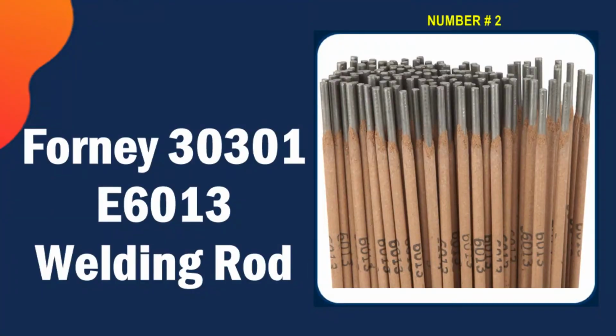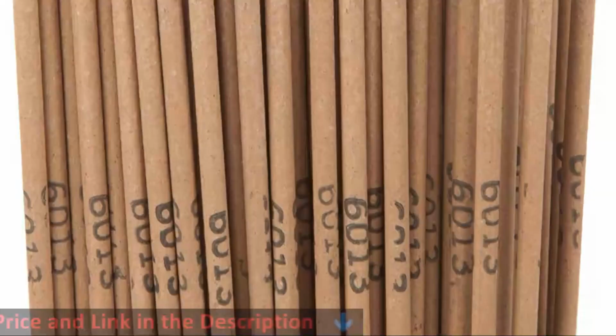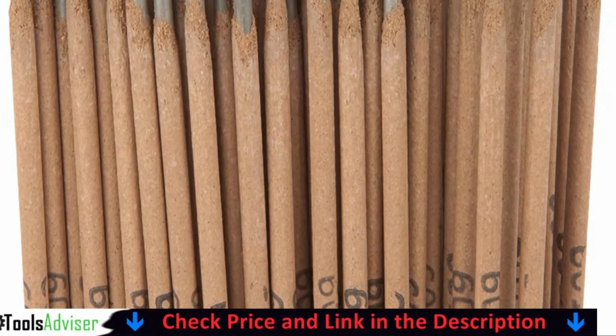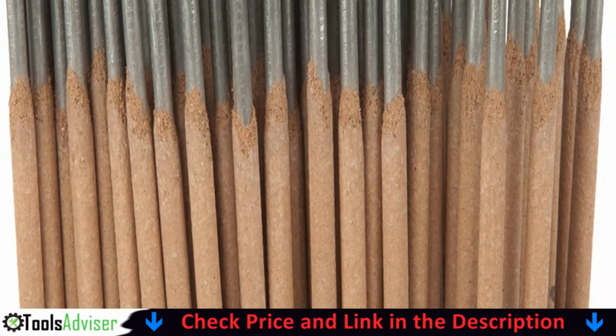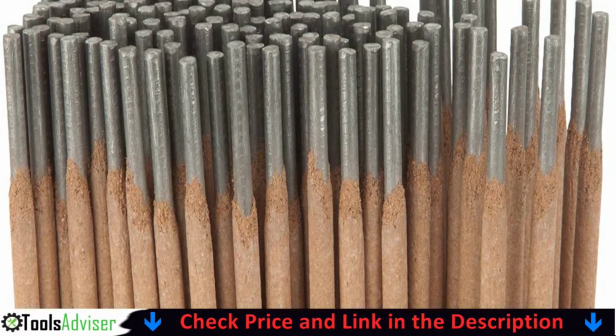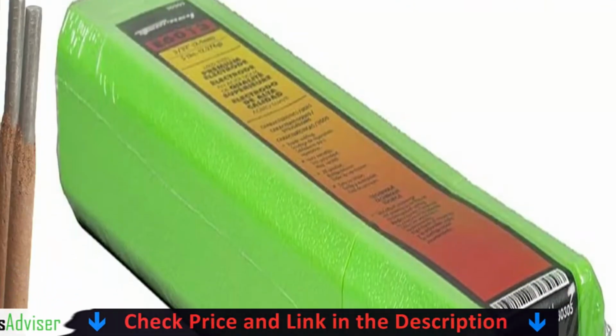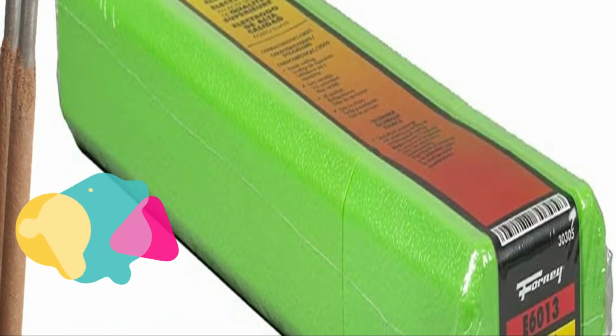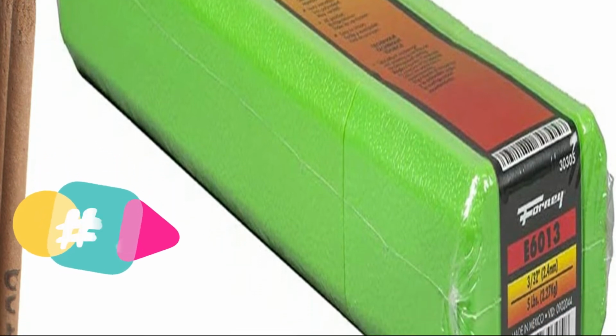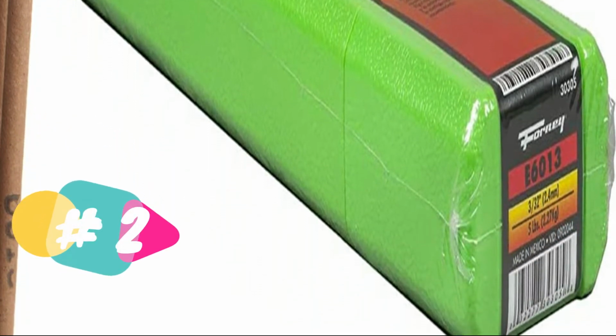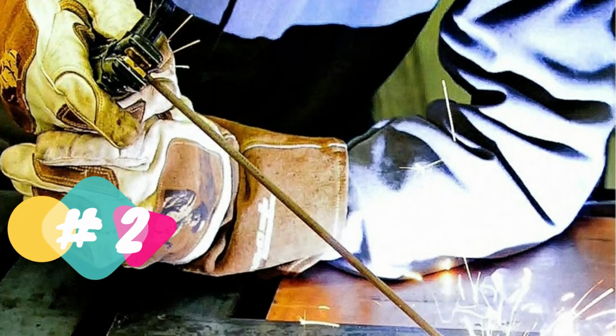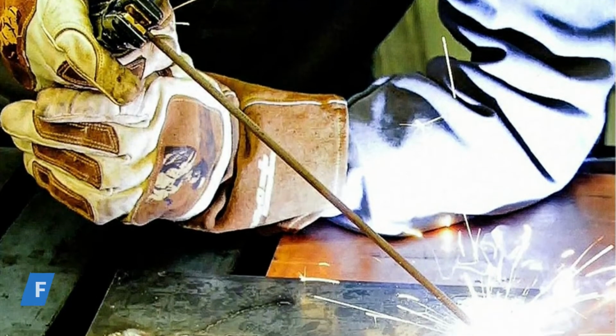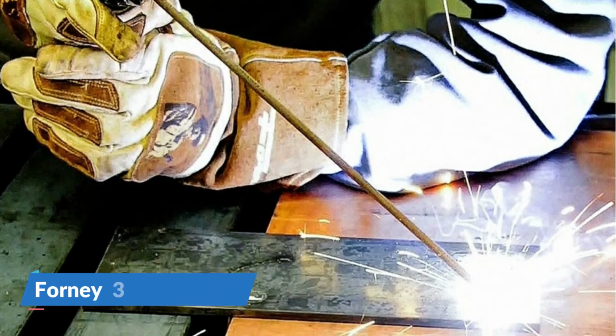Our second best welding rod is the Forney 30301 E6013 welding rod. Thin mild steel tubing is structurally solid and cheap, but some of the most frustrating material to weld. With .060 wall thickness tube, it's almost impossible not to blow through the workpiece. I found these rods to be the most forgiving in this aspect, while still fully penetrating. I can also make significantly longer welds without allowing the piece to cool.